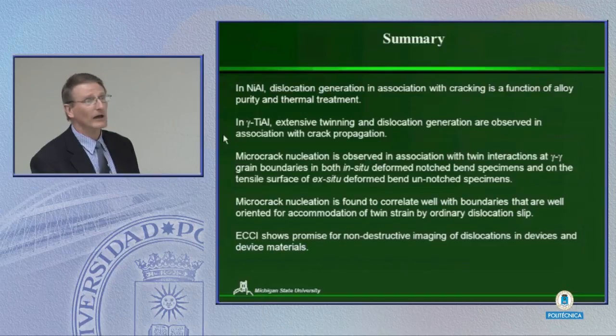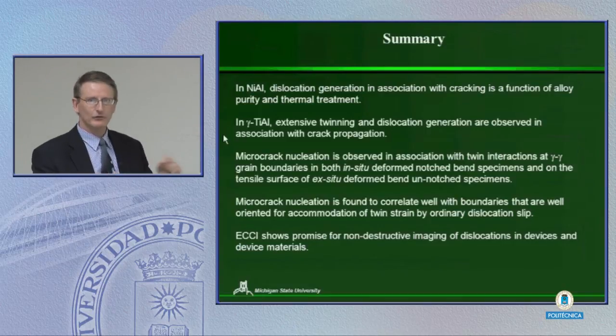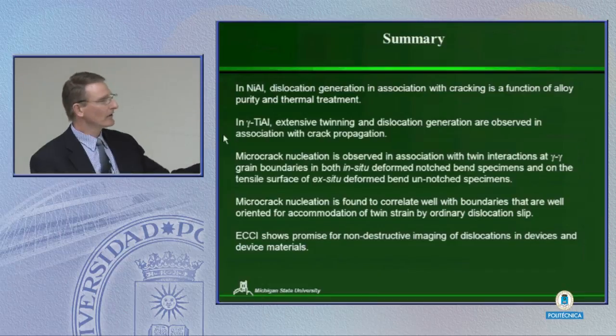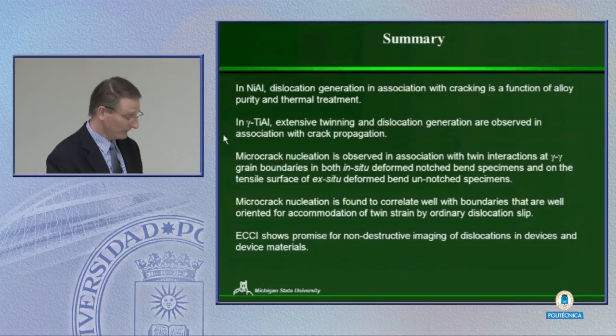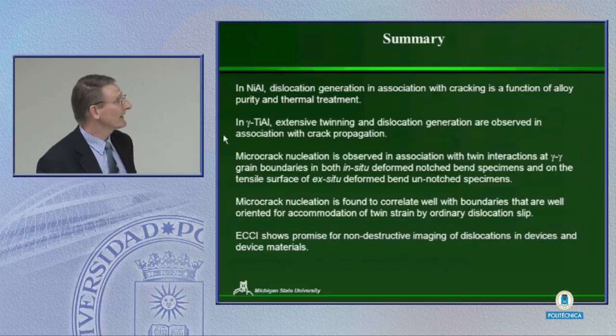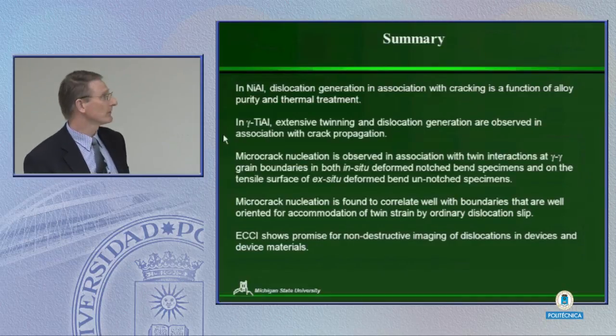We can look at very large areas. With a FIB, you can do some very nice site-selective TEM foil preparation these days. But you still have to take samples from a lot of different places. Here, I can look all over the place without actually damaging the sample. So there's some advantages there. So this makes it very conducive to in-situ experiments.